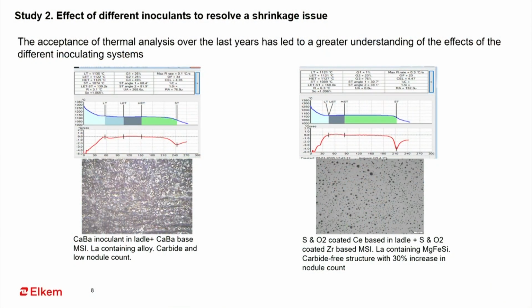So by improving the nucleation potential and using this high performing ferrosilicon magnesium and inoculant both, definitely you can eliminate this microporosity without adding any chill. Most foundries, when there is microporosity or another issue, try to use the chill. But in this case, there is no chill addition. Only by changing this inoculation and magnesium package, the customer is able to produce castings without any carbide issue, without any shrinkage issue.